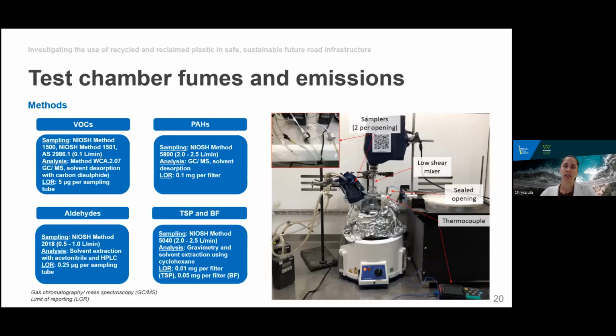We show here the setup for the measurements in the enclosed chamber, where we used a 5-neck flask containing 500 grams of material, and that was placed in a heating mantle. The temperature was controlled at 180 degrees, plus or minus 10, according to continuous monitoring using the thermocouple that was in the bitumen, which was also continuously agitated using a low shear mixer.